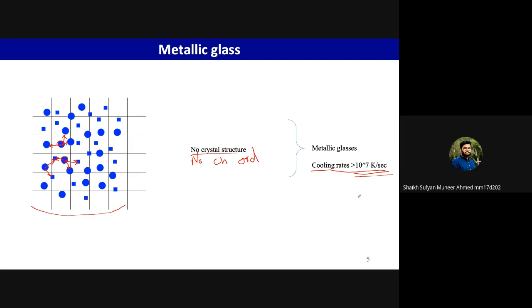When we are manufacturing metallic glass, it is manufactured from a liquid, molten state. When there is a molten metallic alloy, and now you want to cool it, it has to go through nucleation and growth. If you want to suppress that, the nucleation of second phases, of crystalline phases, then you have to have very, very high cooling rates. And this is the reason that high entropy alloys do not solidify into glasses, because the cooling rates are not large enough to overcome these nucleations.